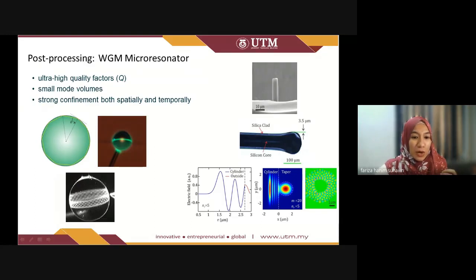The light propagates close to the surface of the structure to give what we call whispering gallery mode properties. So the thousand circulations of light here can produce a very intense light that can lower the threshold for nonlinear effects. That's the very basic understanding of microresonators and how we can transfer this knowledge to the silicon optical fiber.